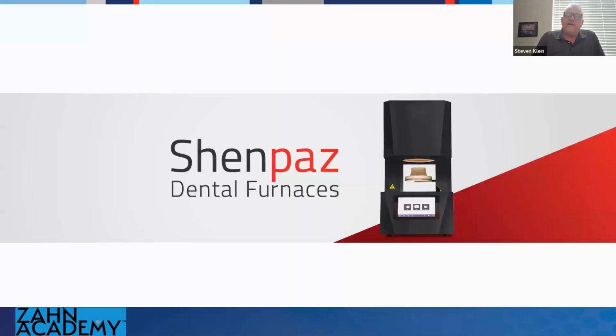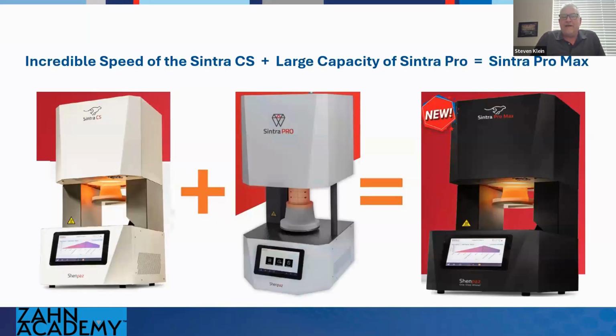And to that note, we're going to talk about the Shenpaz oven today, and most specifically, we're going to talk about the Sintra Pro Max. This particular oven is basically taking the CS, which is the chairside oven, very small chamber but extremely fast capabilities. It can do some seriously quick sintering. But what they've done is create the best of both worlds with the CS oven and the larger capacity of the Sintra Pro, and came out with the Sintra Pro Max. So you have high-speed programs, you have big chamber capacity, even capable of doing full arch in about 3 or 3.5 hours.